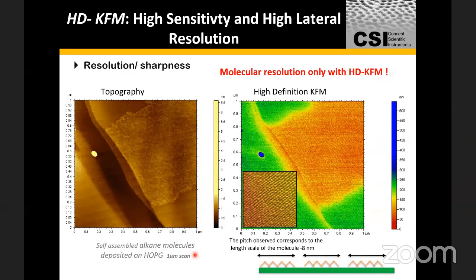However, we can't forget the fact that the tip and the sample's interaction is going to be affected by molecular humidity, for example, and other contaminations on these surfaces. Hence it is quite important, often when you're making electronic measurements, to be able to purge a gas, so that gas makes this tiny contact environment between a nanometer scale tip and my surface as reasonably clean as possible, in an ambient condition, not in a vacuum condition, of course. And this is typically done by purging a gas, and maybe I should come back to what the microscope looks like. So it's going to make it clear to you.